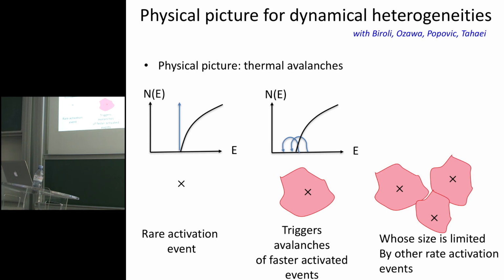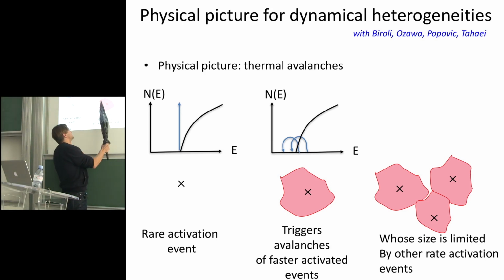So here is a physical picture in a model like this. This is your density of excitation. What's going to happen is that at some point you can have a fluctuation and you can thermally activate one of the excitations with the lowest barrier. Let's say this one relaxes. Because it's relaxing, it's going to give kicks to the activation energy, or xi or E, the same, of sites that are around it. Some will go past this gap value here. Now those are not mechanically unstable. They still have a finite barrier, but they get activated by thermal fluctuation much faster than those ones here. So you can define a thermal avalanche considering the event where you keep having sites below the gap value. And this will grow in time.